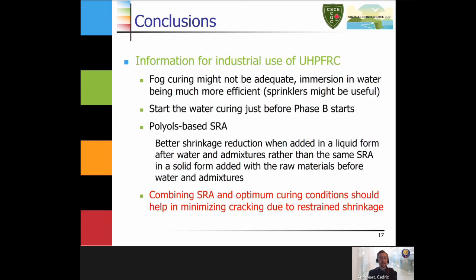So this brings information really interesting for the industrial use of UHPFRC. First, the fog curing might not be really adequate. We've seen that immersing the specimen in water is much more efficient. So maybe we should think about using sprinklers, for example, to apply that information for industrial use. Another thing is that we've seen that the starting time for water curing is optimum just before phase B starts. So if you want to control the best we can the shrinkage, and especially the early age shrinkage, we need to control the starting time for the curing.